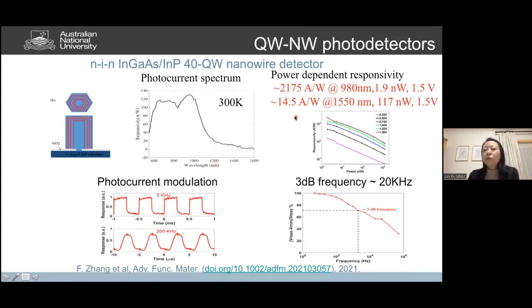And then this quantum well photodetector also has very good responsivity, due to the transport inside, the radial direction transport. And also we can modulate them at about 20 kHz at 3 dB frequency, which shows they are relatively fast as well. So we're showing that these indium gallium arsenide/indium phosphide quantum wells can also be used for photodetector application.